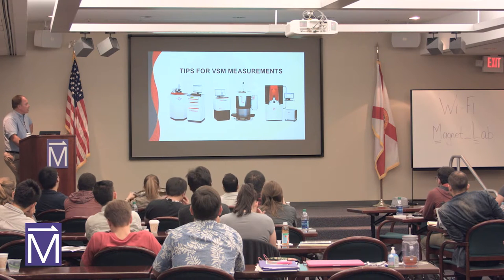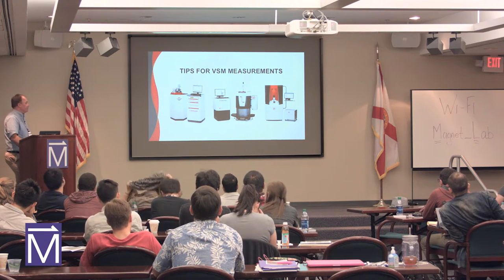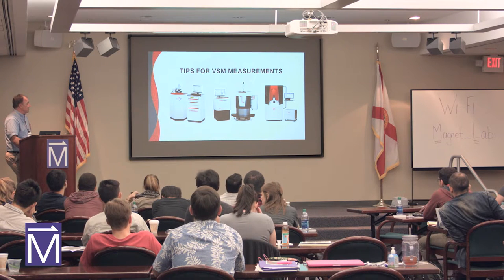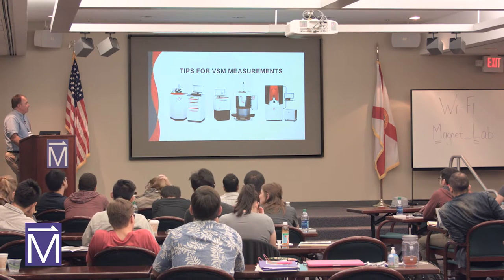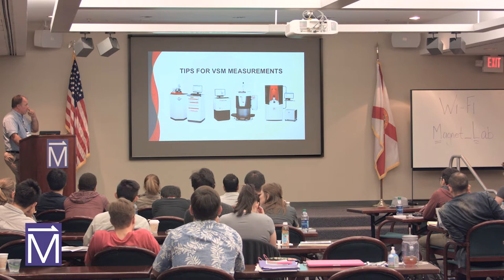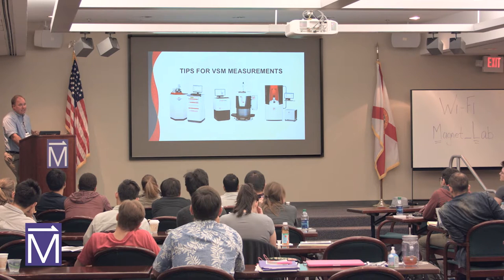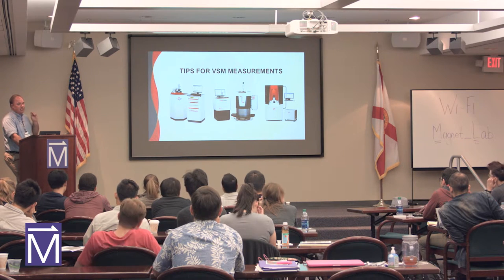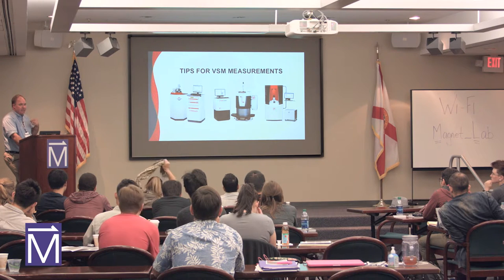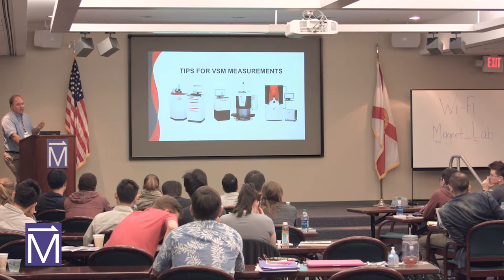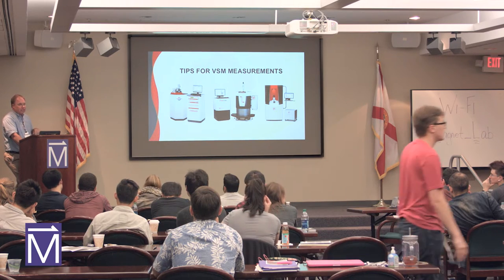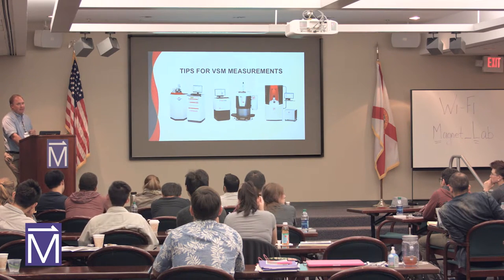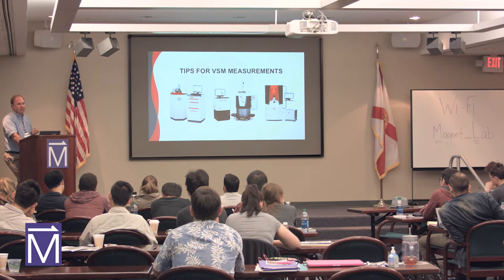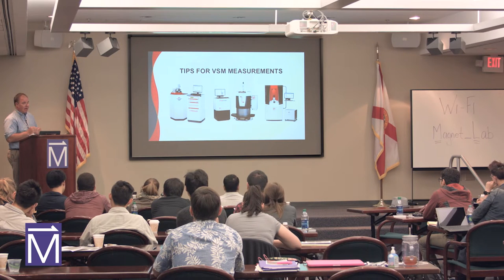And now let's change gears, and we'll talk a little bit about tips for making some of the magnetometry measurements on the systems. So typically you're doing the VSM measurements on the PPMS Dynacool series. The SQUID magnetometer has a VSM mode to it, but it's using the SQUID to make the VSM measurement. Typically the SQUID measurement for magnetometry for those hysteresis curves is a DC SQUID type method. With the SQUID you have 10 to the minus 8 EMU sensitivity. The VSM technique is 10 to the minus 6 EMU. So you've got better sensitivity with the SQUID magnetometer.